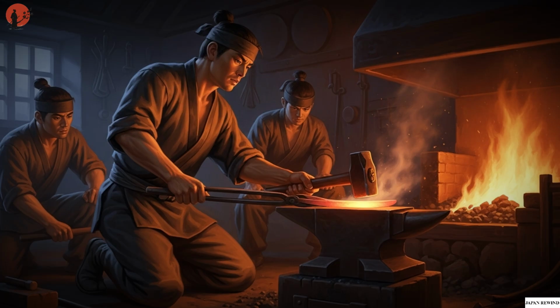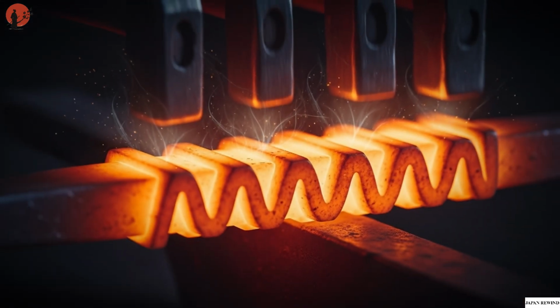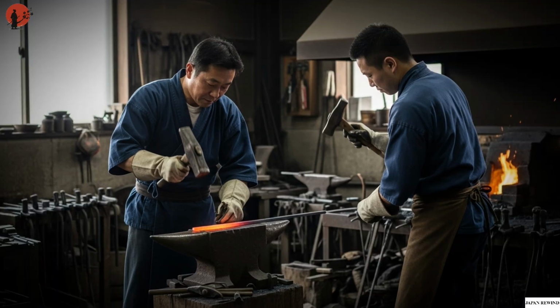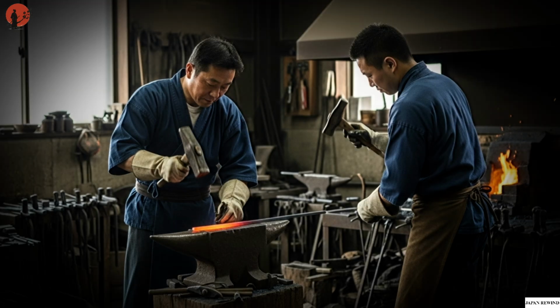The folding would begin. Known as orikaeshi tanren, this folding process was far more than aesthetic. Each fold refined the grain of the steel, drove out trapped impurities, and homogenized the carbon content. After every cycle, the billet was reheated, elongated, and folded again. Some blades underwent 10 to 15 folds, resulting in thousands of microscopic layers. Too much folding, however, was dangerous. Excessive folds could dilute the carbon and weaken the steel.